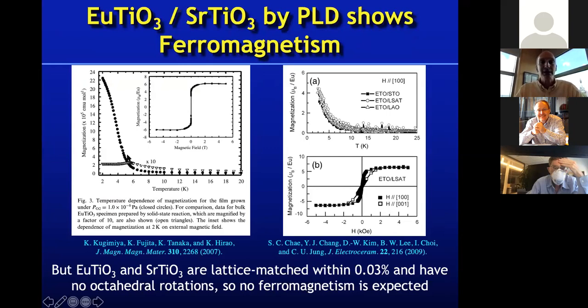Okay, these are thin films grown by these different groups on strontium titanate. This is the non-magnetic version of europium titanate. It has a lattice constant of 3.905. Europium titanate has the same lattice constant within experimental error. So these things are beautifully lattice matched. They have no octahedral rotations. They're both cubic materials. So how is it that when you make this thin film on a lattice matched substrate with no rotations, you should not see ferromagnetism? And what this group saw in their film is clear ferromagnetism.